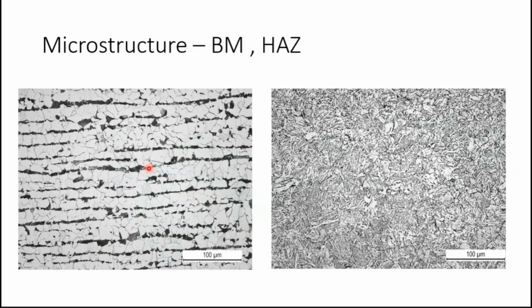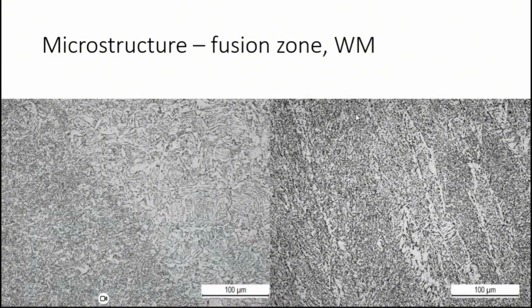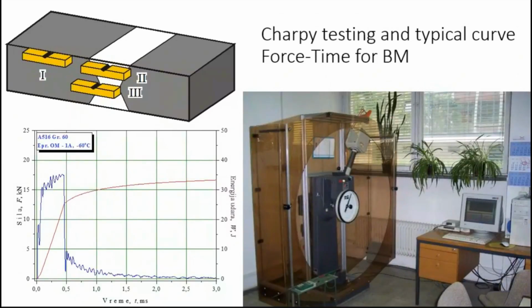Microstructure, typical for this type of steel, and then for the heat affected zone and for the fusion zone and for the weld metal, a pretty different type of microstructure, although you will see that behavior from the point of view of impact toughness is maybe even unexpectedly similar. When I first saw these microstructures, I thought the difference would be much more expressed. So the Charpy instrumented pendulum is almost forgotten but a very practical tool to at least estimate, if not evaluate, material behavior, material resistance to cracking.